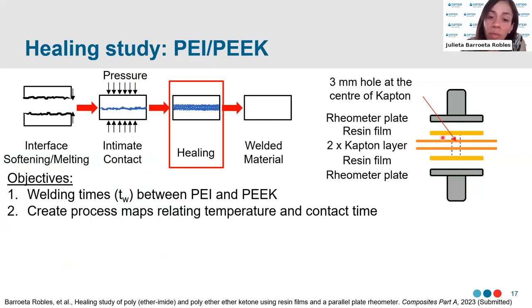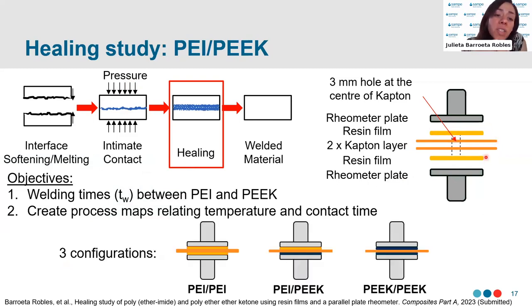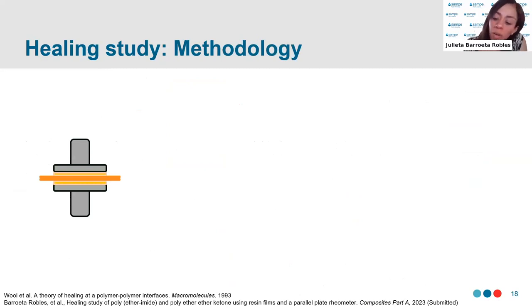Then on top of it, there was another layer of resin polymer film. Now this would be to allow contact between the two resin polymer films. There were three configurations being explored again, where PEI and PEI was used on top and bottom, PEI and PEEK, and then PEEK, PEEK. So in terms of the methodology, the specimens were placed in the rheometer and the temperature was increased up to different healing temperatures.